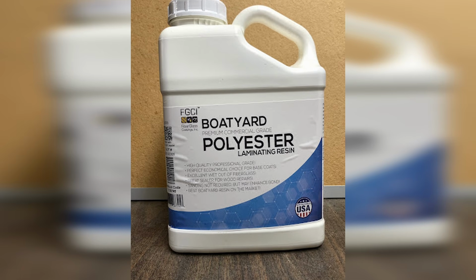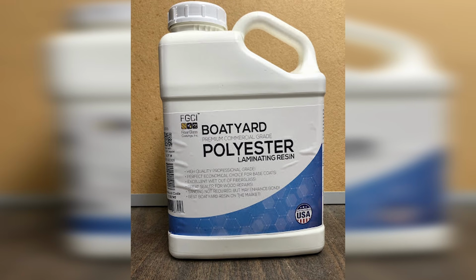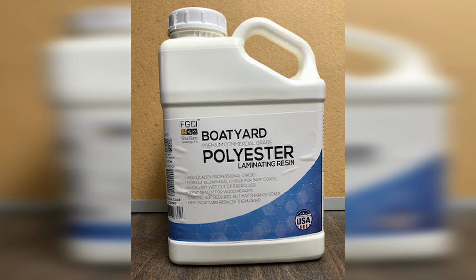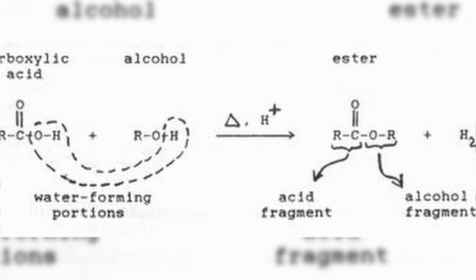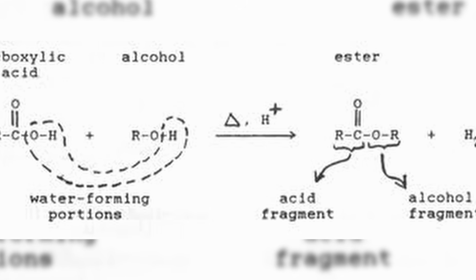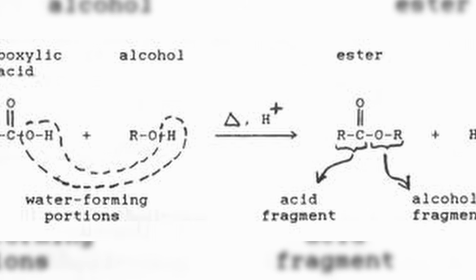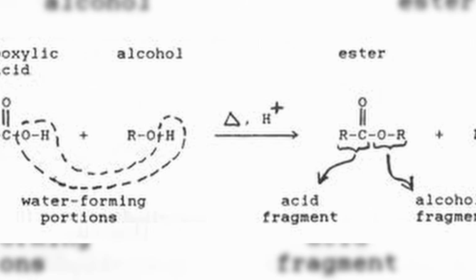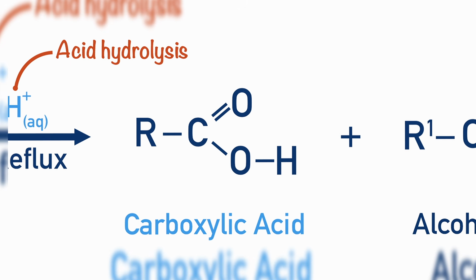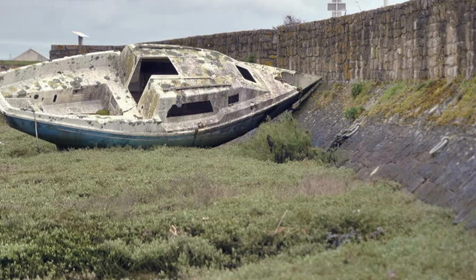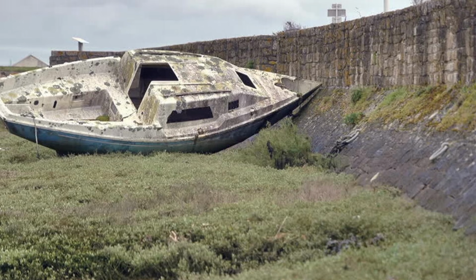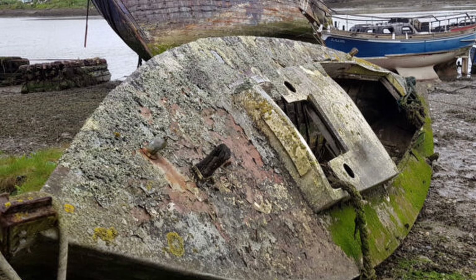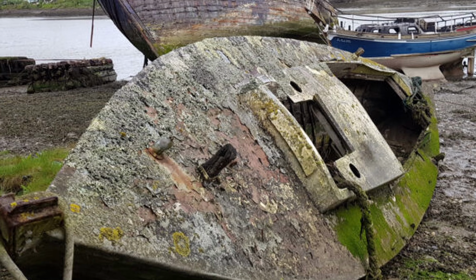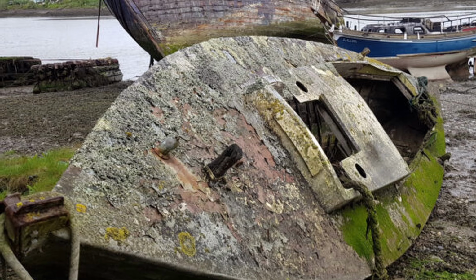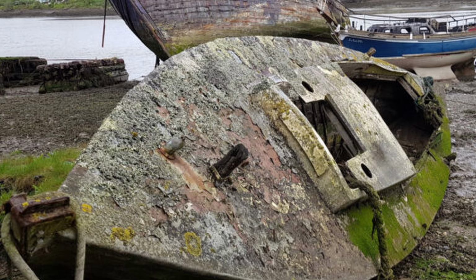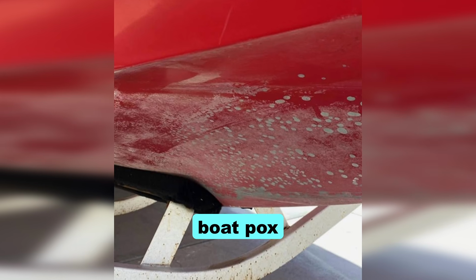Remember that polyester resin is an ester, a chemical compound formed when an acid reacts with an alcohol. The problem is this reaction can run backward. When water gets into the resin, it breaks the ester bonds. The resin turns back into acid and alcohol. And the worst part, the acid speeds up the process. The more the resin breaks down, the more acid is created. The more acid, the faster the breakdown. It feeds on itself. The industry calls this boat pox.